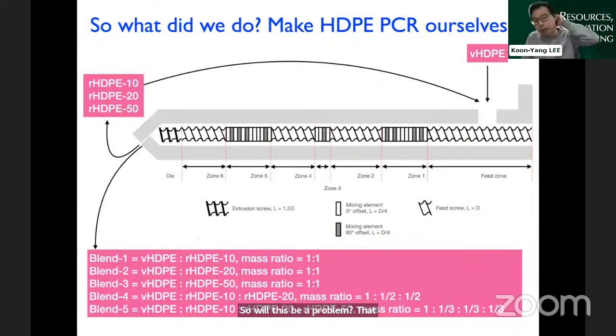So we develop our own ideal scenario here. We start with virgin polyethylene on the top right-hand side corner. You feed into an extruder. You extrude it 10 passes. So you take it out, you put it back, you run it through the extruder, you take it out once again, you do it 10 times. And in that case, our nomenclature here is rHDPE-10 on the left-hand side.